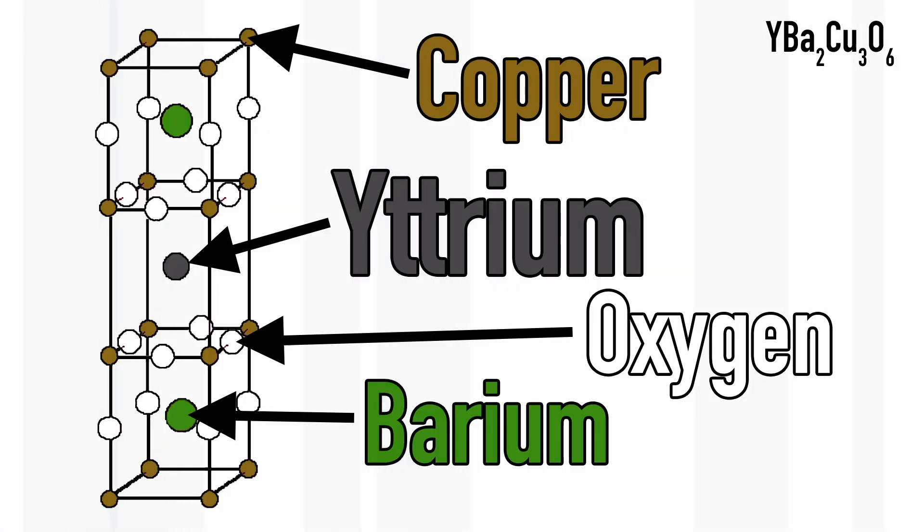It's a really nice demonstration of the Meissner effect. But it's not just yttrium in the superconductor — it's yttrium, barium and copper, a mixed oxide. This mixed oxide has a structure which allows the electrons to flow freely at low temperature. The other application, which was discovered by chance, is also an oxide — an oxide of yttrium, indium and manganese. Yttrium and indium form a mixed oxide which is white, and yttrium and manganese form a mixed oxide that is black.